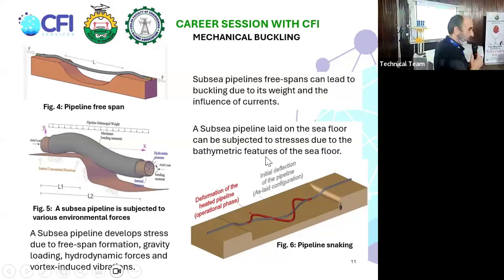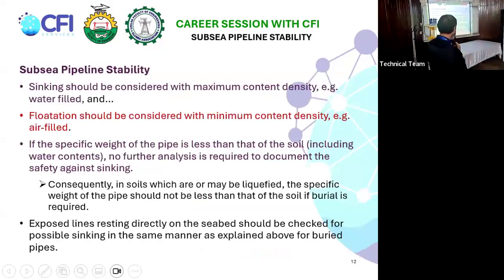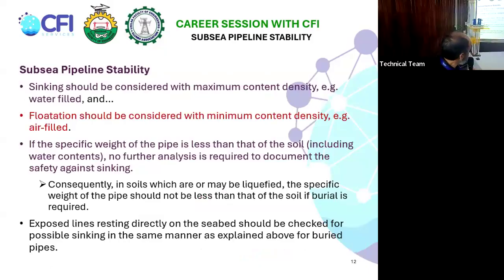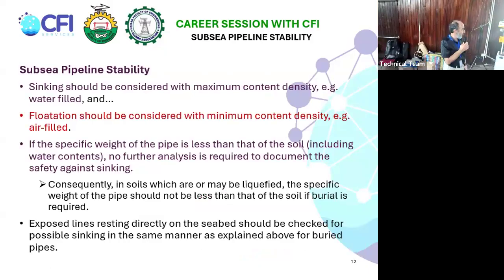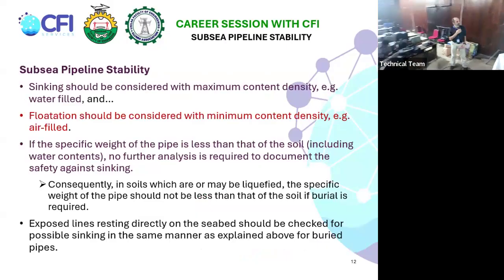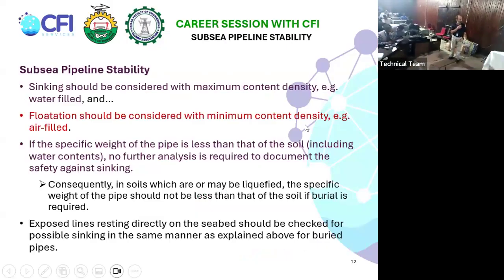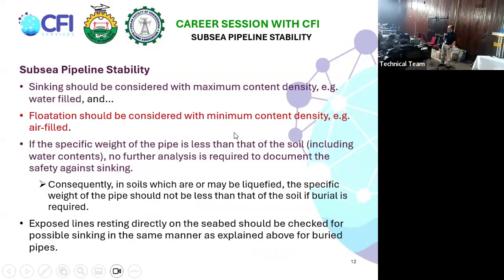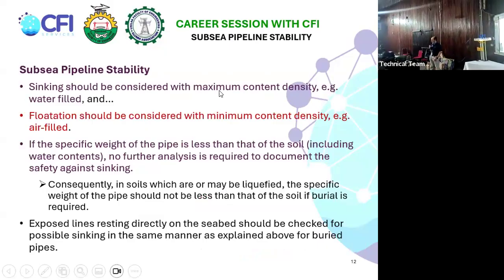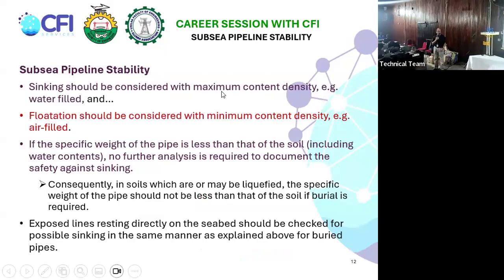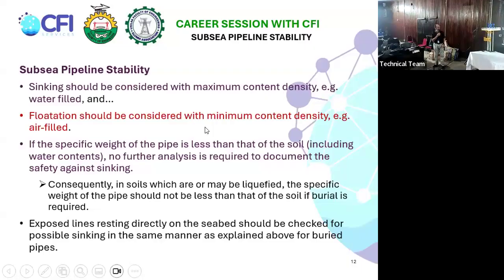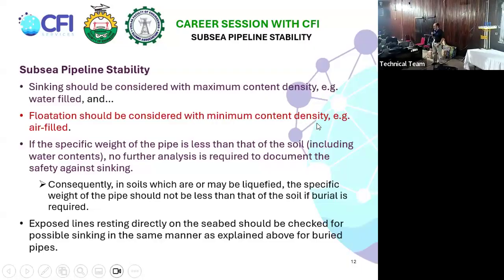So as we were talking already, the pipeline stability. The pipeline stability you can consider based on two parameters. Either the maximum content density, so the pipeline is either water filled or filled with the product to add to the weight of the pipe. Or you can also consider it with minimum density, which is when it's totally empty, full of air. That's when it wants to float, to come up to the surface. And both cases are a stability situation.